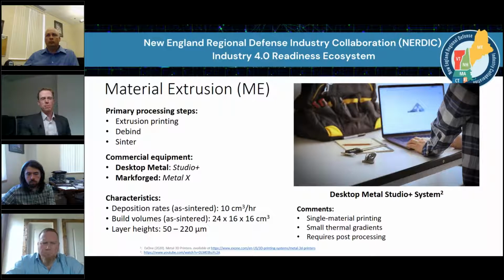Characteristics, typically these types of machines, they'll deposit around 10 cubic centimeters per hour. Layer heights are about 50 to 220 micrometers. And you're printing a single material, and you require some sort of post-processing. We also end up with small thermal gradients, and the fusion process is typically at a small thermal gradient, meaning the object is mostly at the same temperature.